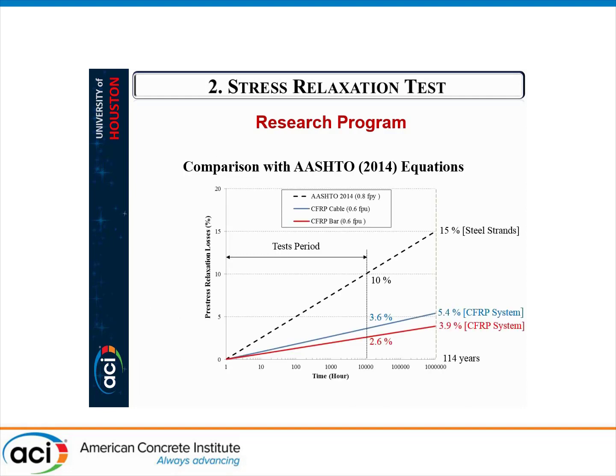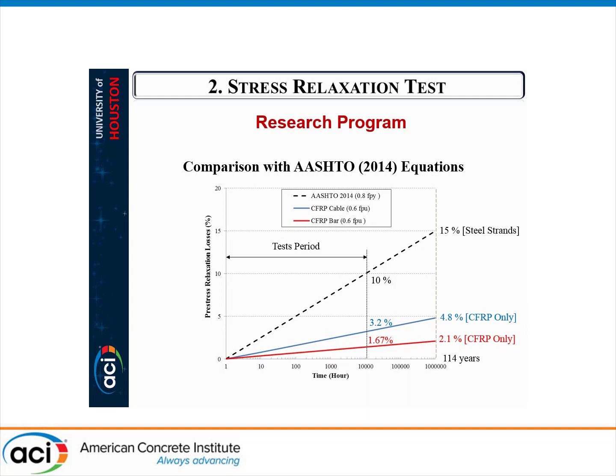And this figure shows the relaxation of CFRP cable and bar compared to regular steel up to 114 years. The extrapolated relaxation of cables is around 5.4%. However, for the bars, we have lower relaxation of 3.9%, compared to steel, which is 15%. And after subtraction of the anchorage losses, we got 4.8% for CFRP cable and 2.1% for CFRP bars.